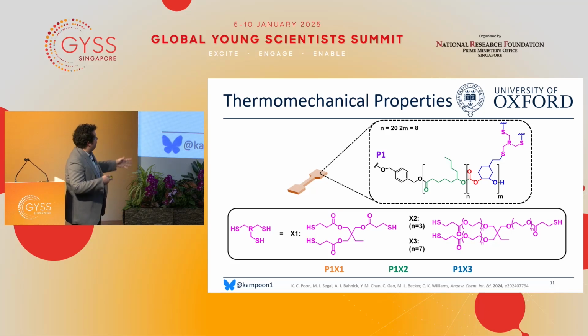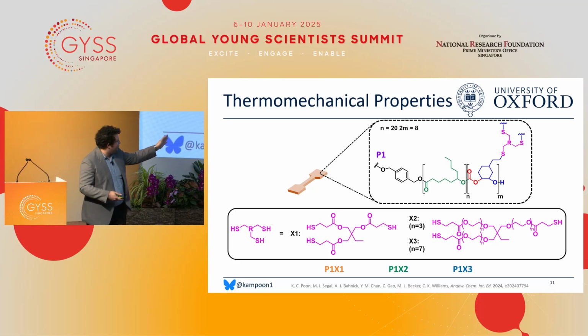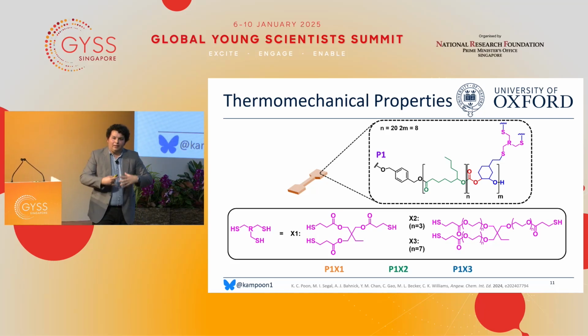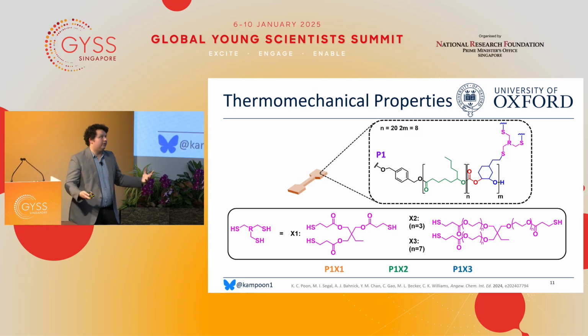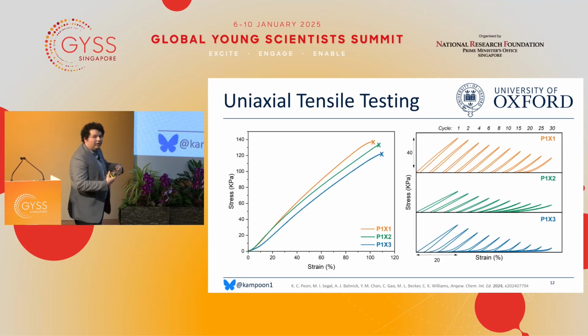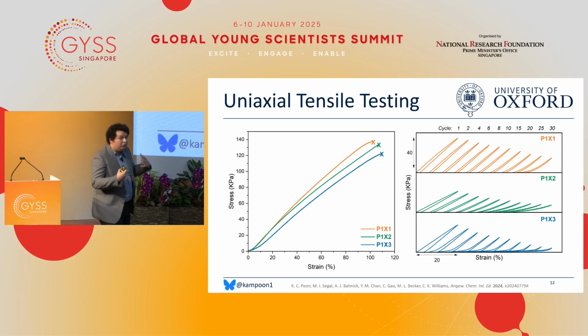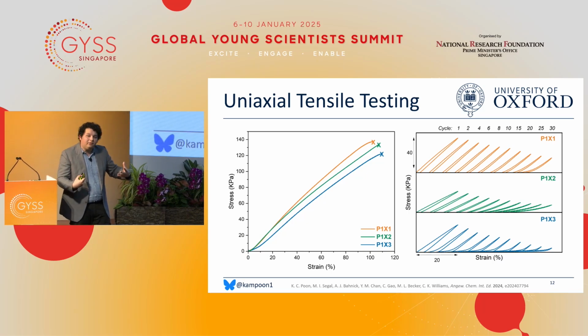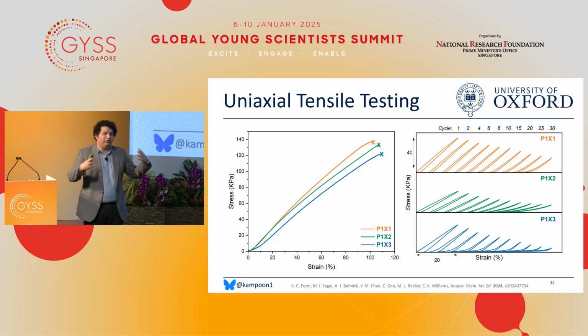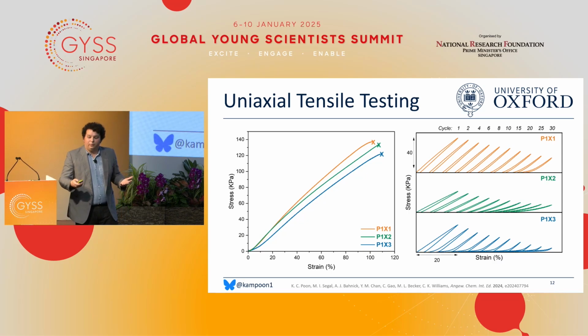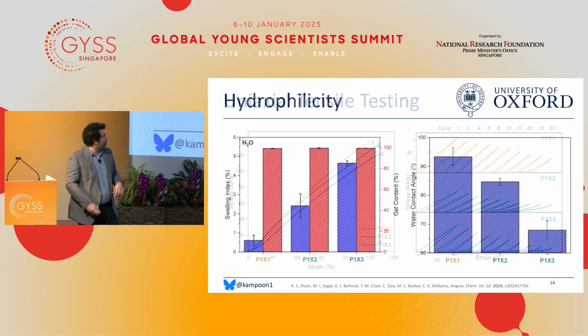So it's a reminder that as we go from P1X1 to P1X2 to P1X3, we're increasing the length of that crosslinker and hopefully its hydrophilicity. If we look at some mechanical testing of these materials and we pull them apart, we can see there's not really much difference between the crosslinkers and the mechanical properties. We do see a decrease in elastic properties as we increase the crosslinker, and that's attributed to the fact that we've got an increased number of degrees of freedom and therefore more hysteresis.